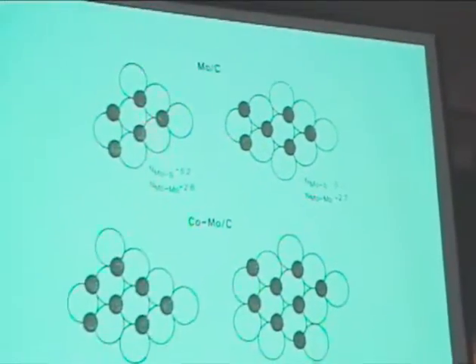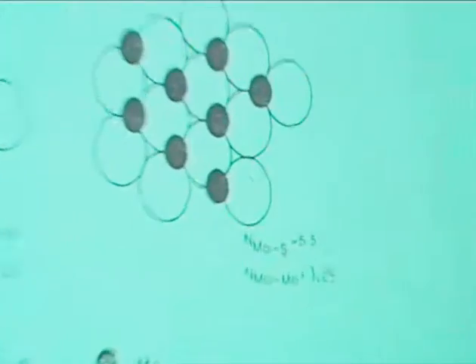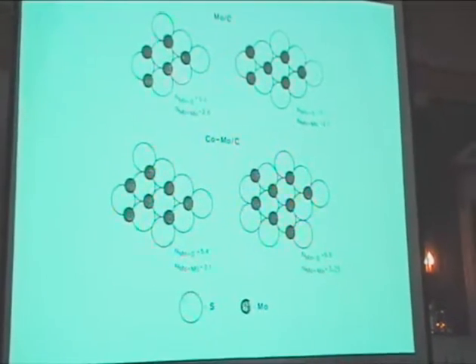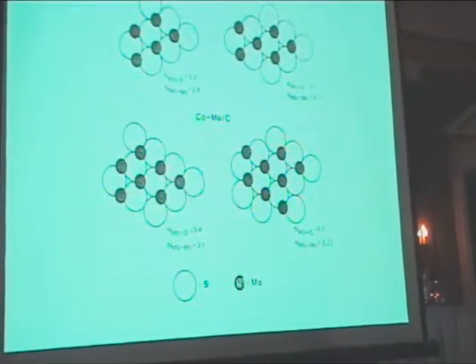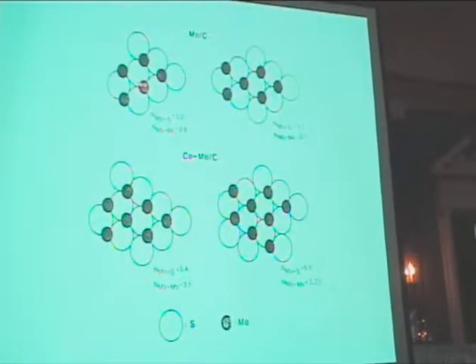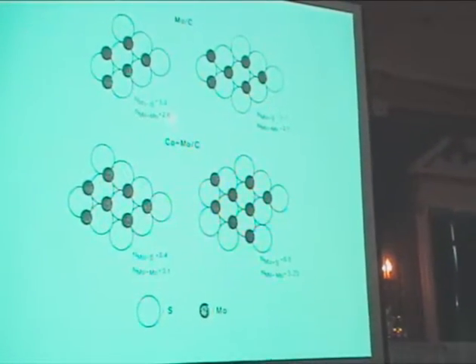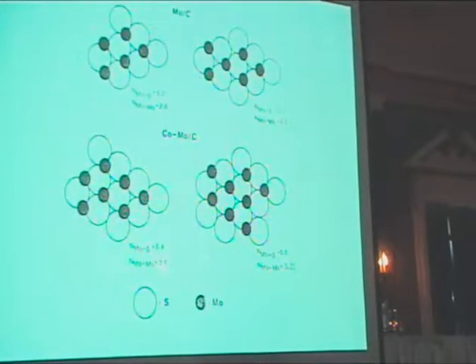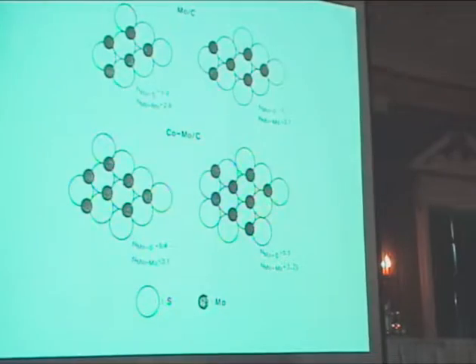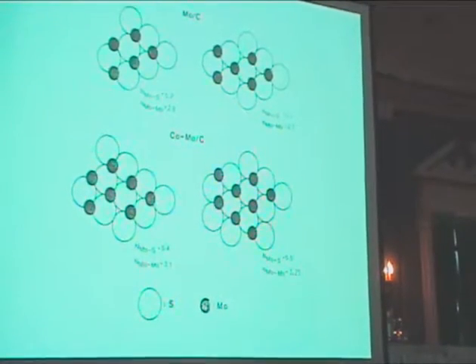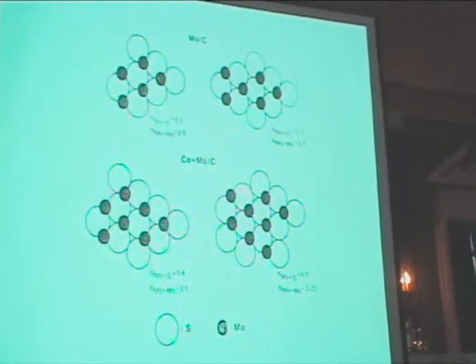So on average, in this case, because EXAFS is a bulk technique, it's an X-ray technique, it looks through my sample. I am looking at every molybdenum atom. So I see this one and I see this one, so my information is averaged. So in this particular picture, the average molybdenum coordination number is 2.8. Here it's 2.7, here it's 3.3, here it's 3.2. So you see, it's low. The analysis of the spectra I showed you of the catalyst gives 4. So maybe the particles are a little bit bigger than this. So it shows you can do, EXAFS in principle can give you information on the size of the crystallites of your catalyst.